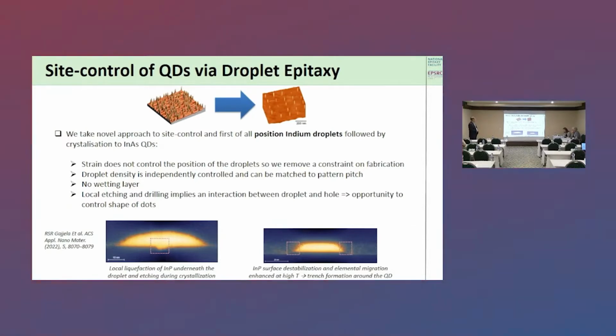Strain doesn't control the position of the droplets, so we can remove a constraint from the fabrication. Because the strain affects the quantum dots in often very subtle ways, we would need to control the fabrication of the nanoholes that we use to seed the dots. But if we remove that constraint, then actually things are easier. So that's a significant advantage.